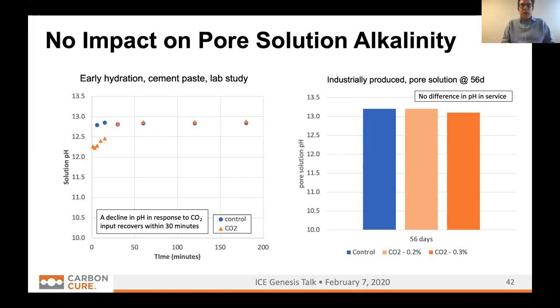If we look at the earliest stages of hydration, so in the first few minutes, yes, you can add CO2 to cement, and yes, the pH goes down. You put carbonate ions into solution that can act as an acid. But that rebounds and you're back to the regular pH of the system after about 10, 20, 30 minutes. So once the reaction has taken place and the secondary effects have equilibrated, you're back to the normal pH. So this reinforces the fact that nothing is happening to the pore solution alkalinity.